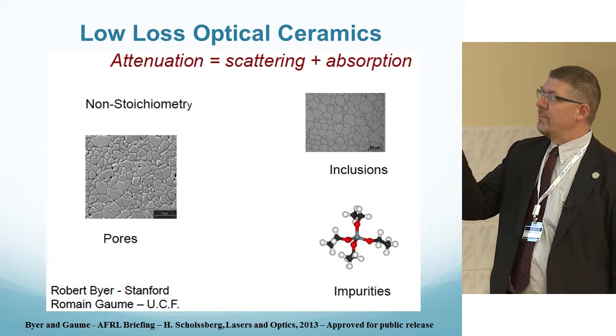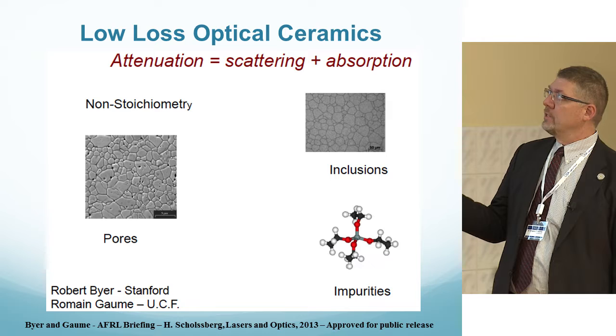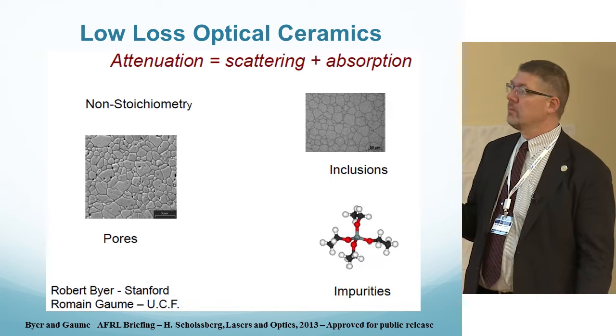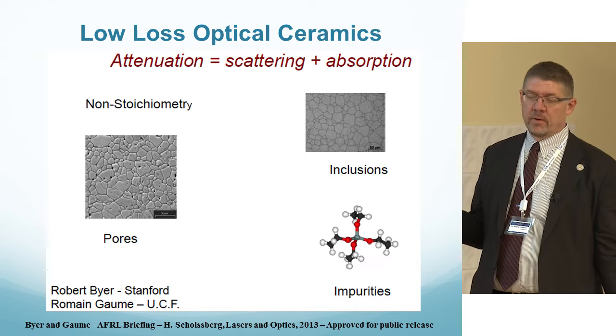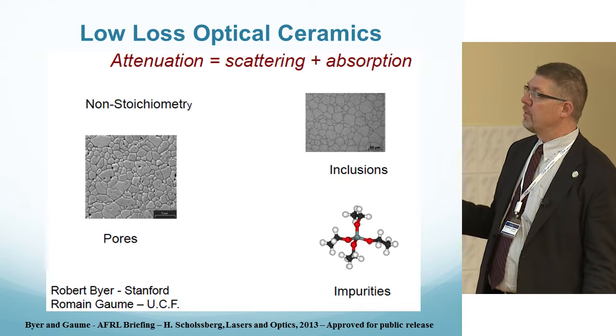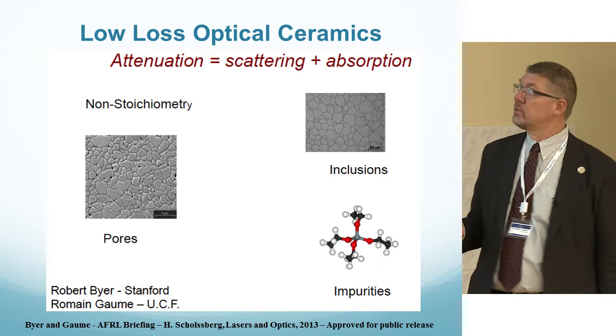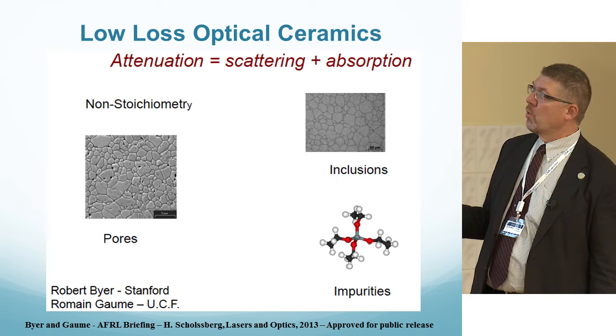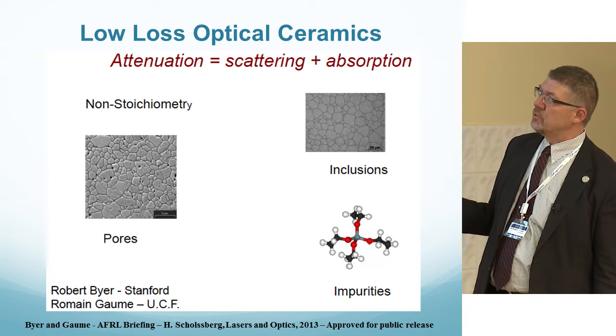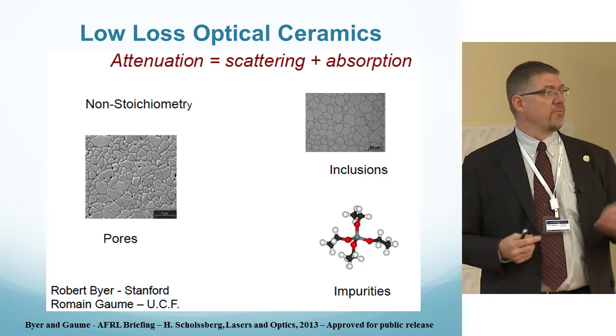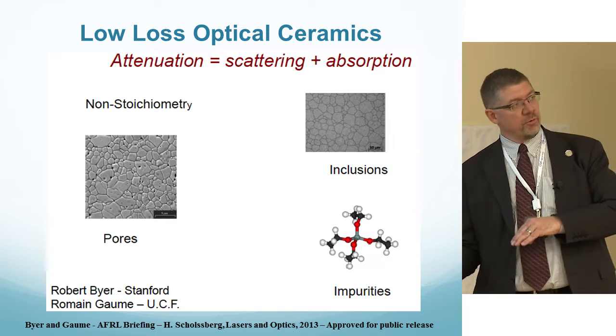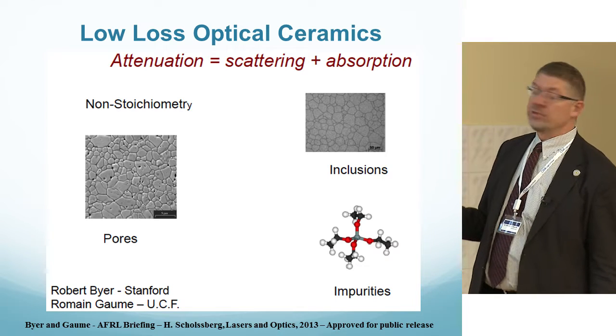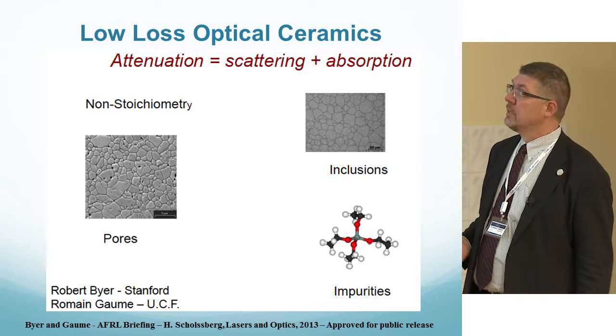So what does that mean? Well, attenuation is scattering and absorption. Absorption you're going to have from the neodymium, but if you have other impurities, you're going to get residual absorption from that. But you've also got pores, which are these little black dots that you see here. That can either come from your material being too rich in aluminum or too rich in yttrium, and inclusions that get trapped inside of the material.